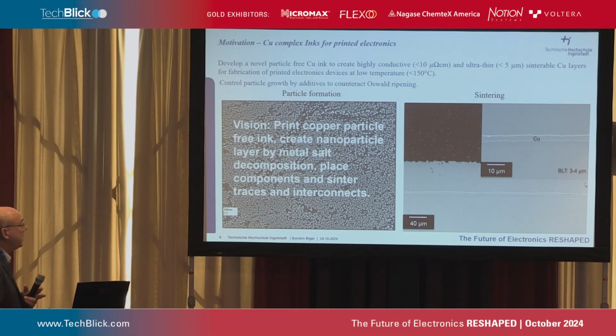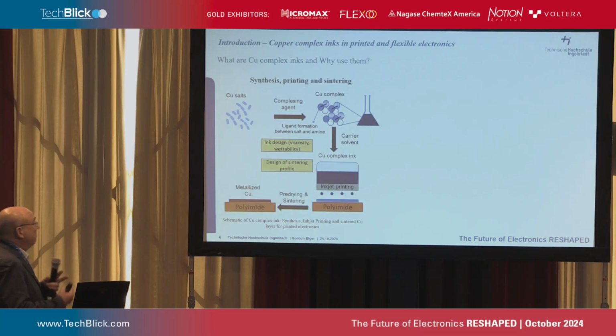So in the end, the vision for printed electronics is that we print the traces. We then have to dry the ink, form the particles, place also components, and then do sintering of traces and of components in one step. That's the vision which we are following. So what is the ink? In principle, you start with the copper salt, you add the complexing agent.